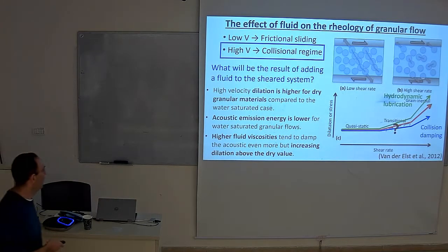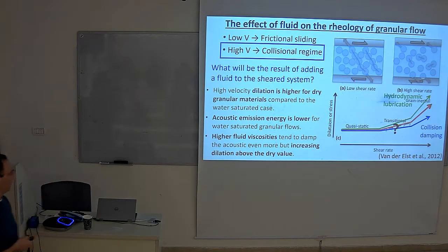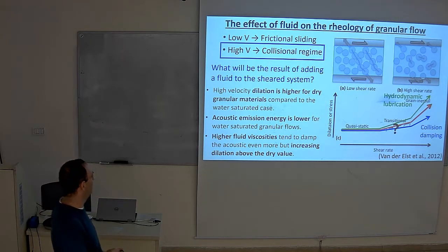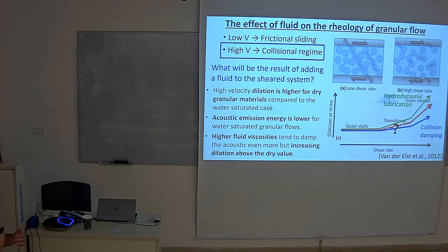So to summarize, I think we have some insight about shearing in the presence of fluids. Dilation is higher for dry granular materials, at least in comparison with water. Acoustic emission energy is lower for water-saturated granular materials, and high fluid viscosities tend to do the opposite, more dilation actually, but the acoustic energy is decreasing. So dilation and stress, we can add to this graph the collisional damping, which is mainly controlled in pure water, and hydrodynamic lubrication effects if we increase the viscosity of the fluids.